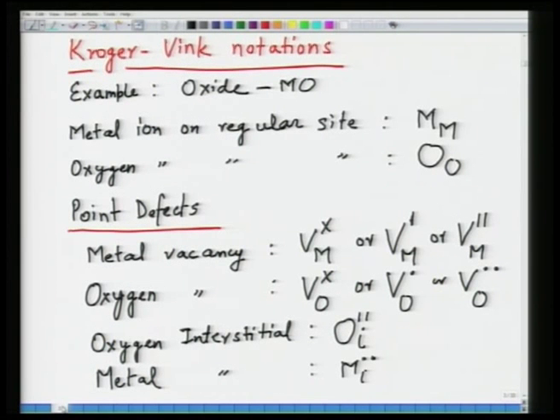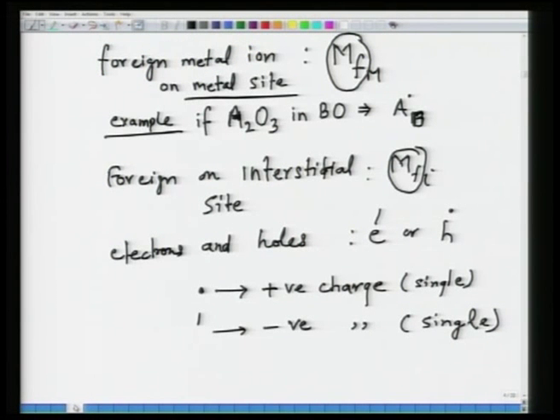And then we introduced the Kroger-Vink notations, where each defect, whether charged or uncharged, has a particular notation by which it is denoted. In a nutshell, if a defect is positively charged, then it is denoted by a dot on top of it. For example, in case of oxygen vacancy, you write it V_O double dot if it is completely ionized, and in this course we will assume that all the defects are completely ionized. And if it is a negatively charged defect such as metal vacancy, then it would have a dash. One dash would mean single charge and two dashes would mean double charge, and so on and so forth.